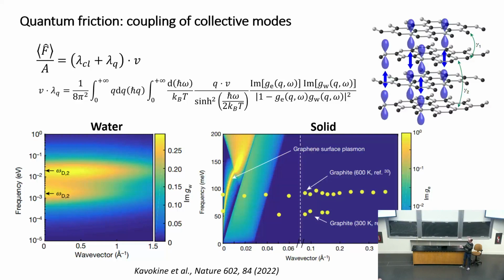Okay. This is a bit hand-waving, but water has what's called the Debye peak, that has pretty low dispersion when you look at the wave vector, but it has this peak here at a couple of 10 milli-eV. Now in the solid we can actually distinguish. In this study they looked at what graphene does. Graphene has the surface plasmon here, which shows very big dispersion, versus what graphite does. Graphite has low-lying surface plasmon modes, which are in the z direction of the graphite, and these modes don't even show any dispersion here.